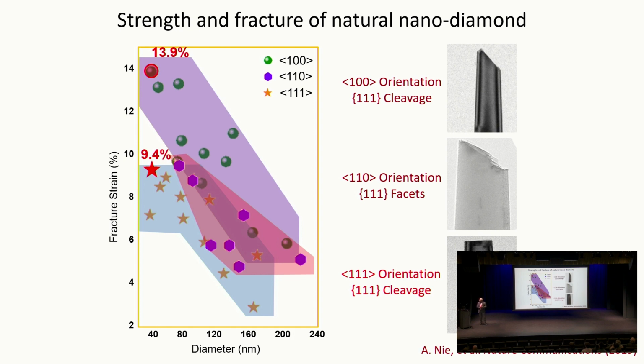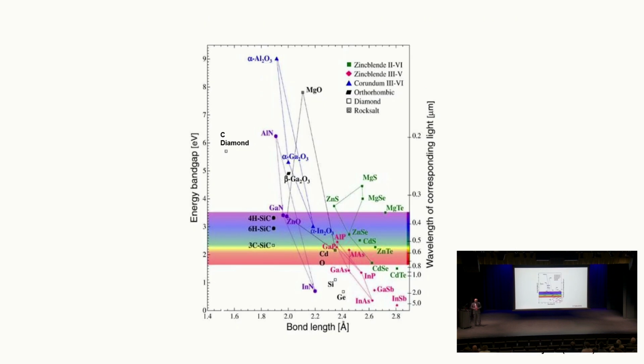And in certain orientations, they were able to go as high as 13%. So the results were independently confirmed in natural diamond by a very different group. Here are the images from their experiments, which were published in 2019. So the next question is, we can bend diamond, so what? What do we do with it?